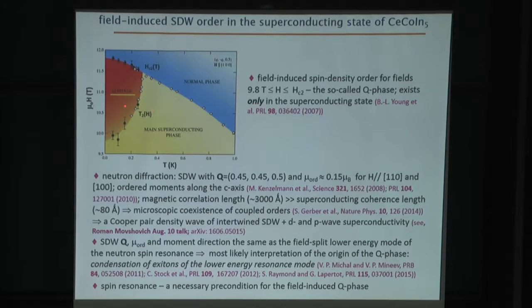And neutron diffraction shows that this magnetic phase is a spin density wave, and it has an ordering wave vector of (0.45, 0.45, 0.5), and the ordered moment is about 0.15 Bohr magnetons, and those moments are ordered along the c-axis. In this phase, the magnetic correlation length of the spin density wave order is much greater than the superconducting coherence length, which implies that the magnetism and superconductivity coexist, and furthermore leads to the possibility that the magnetism and superconductivity order parameters are coupled. And theoretically, this coupling of the magnetic and superconducting order parameters can lead to what's called a Cooper pair density wave, that is the intertwinement, essentially, of spin density wave order plus d-wave superconductivity plus p-wave superconductivity.